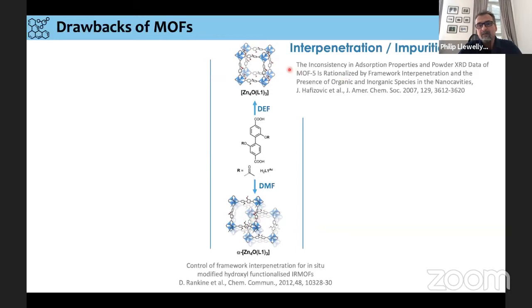Now, the things that have been seen is that for some of these MOFs, the activation or the liberation of the porosity is not always easy, and sometimes there could be organic species or inorganic species that stay inside. And this again can cause problems in some materials. So even though the synthesis seems often, or at least from an outside point of view, fairly simple, the activation and making sure that everything is pure and works well is quite a challenge.